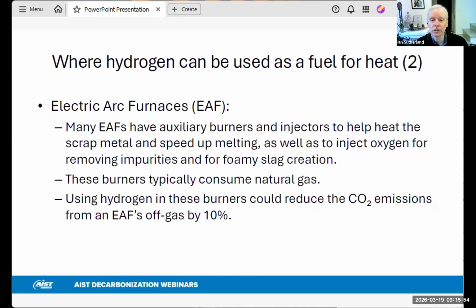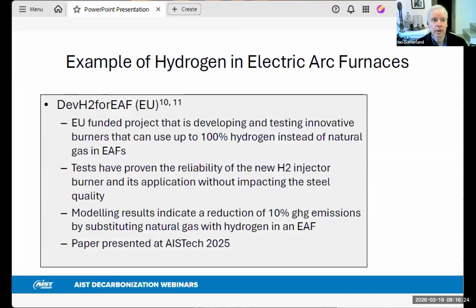Surprisingly, hydrogen can also be used in electric arc furnaces, and this is because many EAFs use natural gas as a supplemental source of thermal energy to help heat the scrap metal and speed up melting. And simulation modeling has shown that using hydrogen instead of natural gas could reduce the carbon dioxide emissions from an EAF's off gas by up to 10%. And this is an example of where the use of hydrogen in an EAF is currently being researched.